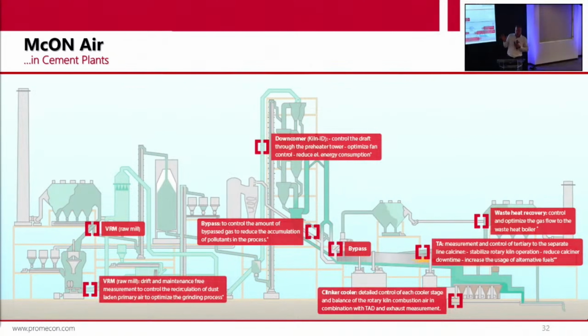Any problems with high NOx on your cement plants? Well, check your pre-calciner. The pre-calciner has fuel, and it has a huge amount of combustion air coming from the tertiary air. Nobody measures it. Why? It contains dust, very abrasive dust. It's clinker. It's 1,000 degrees hot. How can you measure this?